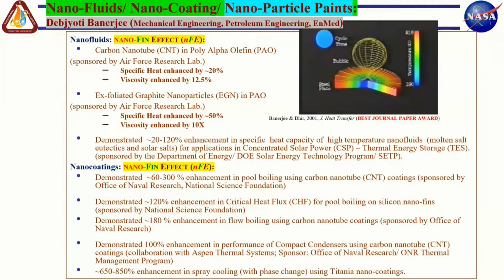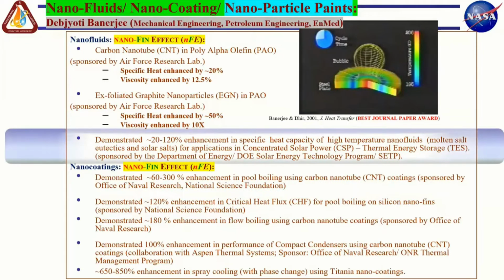So at that time, we could not make sense of it, but we pitched this idea to DOE, Solar Energy Technology Program, for molten salts. And molten salts have very poor thermal properties, both in terms of thermal conductivity and heat capacity. And by that time, I had about 4 PhD students working on this project, and we were able to crack that nut. We figured out what is responsible for this enhancement, and once we understood the beast, we could control it, and we could actually double the heat capacity of molten salts for solar thermal applications.